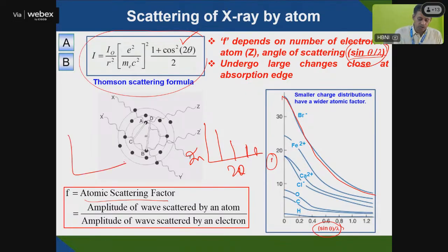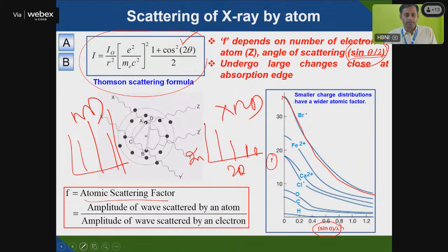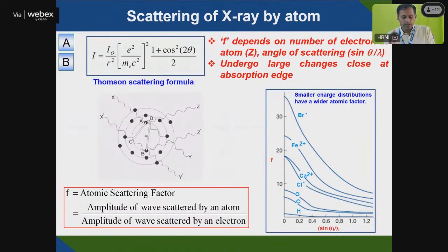But this is in XRD. In neutron diffraction, which we'll discuss later, it is random. There you can also get the most intense peak at higher angle. That is mainly because here there is no dependency on sine theta by lambda. Instead, it depends on the scattering length, which randomly varies. Okay, so this is the scattering factor.